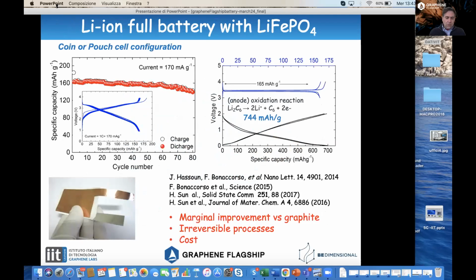But just to give you a few hints about the results, a few years ago, we demonstrated with Bruno Scrosati a lithium-ion battery using a lithium iron phosphate cathode and a graphene anodic material. We demonstrated the battery, but we also demonstrated that the improvement with respect to the technology using graphite is marginal.